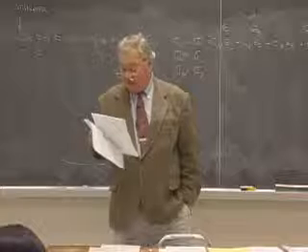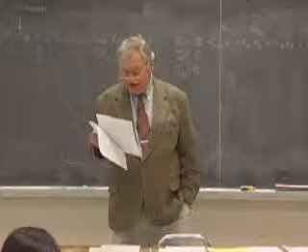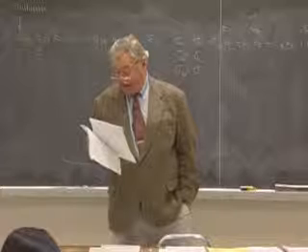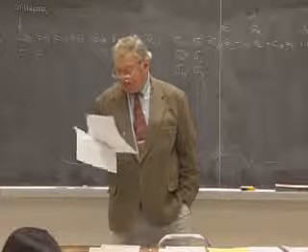Sijkl is Smn if M and N are 1, 2, or 3. That is to say, not 4, 5, or 6. Sijkl, which is the same as Sijlk, has to be defined as 1/2 of Smn, where M or N is 4, 5, or 6. And then finally, you have to throw in a factor of 4 when both M and N are 4, 5, or 6, or in other words, M and N are not 1, 2, or 3.